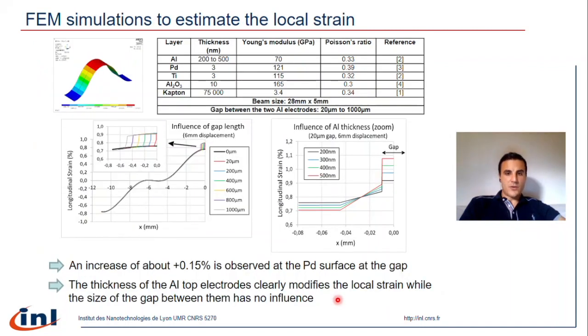In order to better understand the crack formation process, we have developed some FEM simulation with Ansys software. The idea was to estimate the local strain within the gap between the two aluminum top contacts. The parameters that were used in the model are presented here in this table on the top. First, we have plotted the longitudinal strain as a function of the position on top of the surface of the sensor. We have simulated half of the structure.